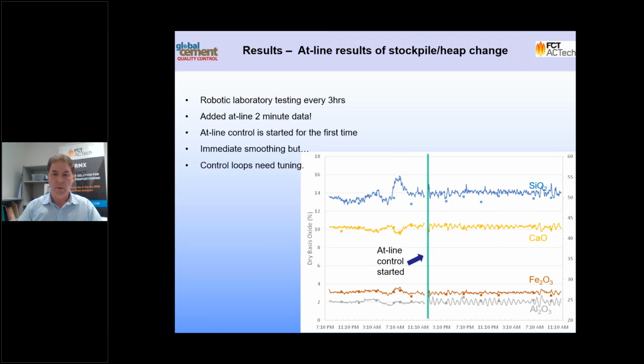So just adding a bit more information onto this graph, I've got a line here, and this line represents the point at which the automatic control system was turned on for the very first time. You can remember back here, some 6 hours prior, we had the heap change, and there's a reasonable amount of variability in that heap. And then at this point, we turned on the automatic control system and it started to manage the operation of the feeders for the very first time.